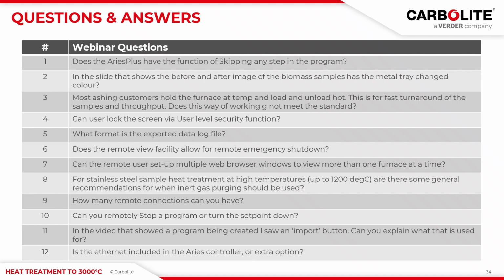Okay. Number 2, in the slide that shows the before and after image of the biomass samples, has the metal tray changed colour? Yes, it has. So if you look back at the slideshow, you'll see it's changed to quite a distinct blue colour. The tray's made out of Inconel, and that material will change colour with temperature. So it's an indication it's been to a certain temperature. And I think a good point is that the colour is very even, so it shows that the uniformity of the furnace is good. So yes, it's changed colour.